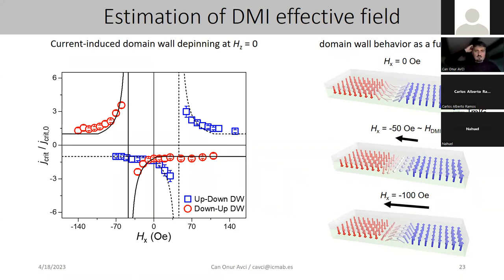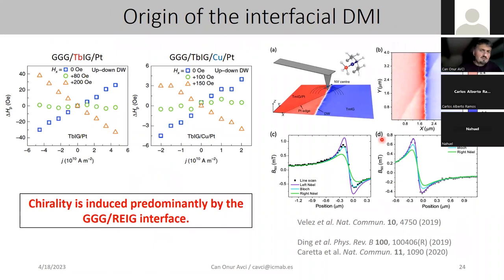Okay, so then we wanted to understand the origin of it, which can only be the interfacial Dzyaloshinskii-Moriya interaction. Therefore, we said, okay, if it's an interfacial effect, it should change if we go to another garnet. For instance, we changed thulium garnet to terbium garnet, and again we see the same behavior. Okay, so you need to believe me here. I will not explain all the details, but the DMI was there again with the terbium garnet.